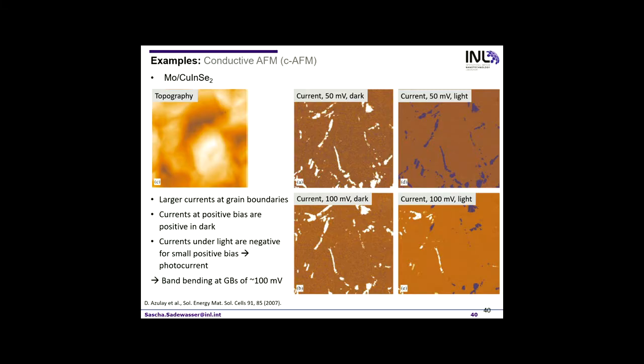And again, grain boundaries. So this is a copper indium diselenide sample, and what they did again here, you can see the topography, and then they observed if they apply a bias voltage. So now you have to apply this bias voltage between tip and sample, a DC, and in the dark they applied 50 millivolts and 100 millivolts, and they see these larger currents right at the grain boundary.